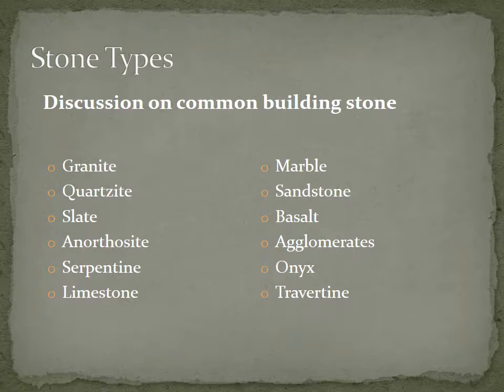The serpentine is the hydrated magnesium silicate. It doesn't polish quite the same as marbles. It has dolomite veins, which are very acid sensitive. With most polishing powders that are made for marble, if you use it on serpentine, it won't quite bring up that green, but these white veins will just jump out and you'll have a real inconsistent finish there. So serpentines need to be polished mechanically much more than with a chemical reaction from some of the acid polishing powders.